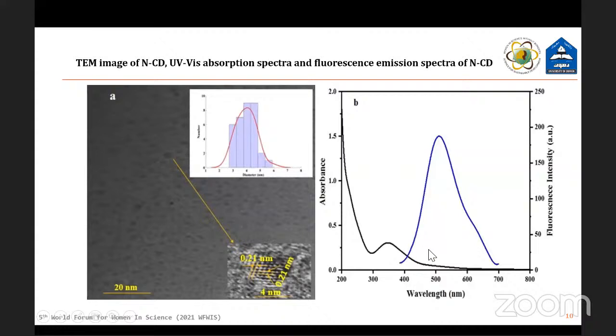And the UV visible spectrum shows a peak at 365, which is for n to pi transition, and also a peak at 260, which is for pi to pi transition, which indicates the formation of our nanoparticle. And the fluorescence emission peak is near 500 nanometer for our nanoparticle.